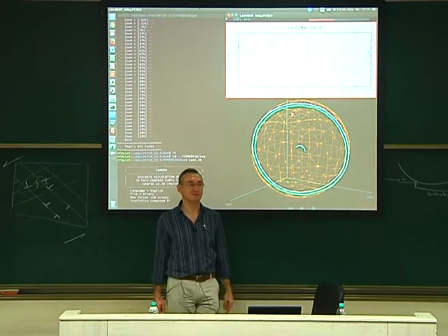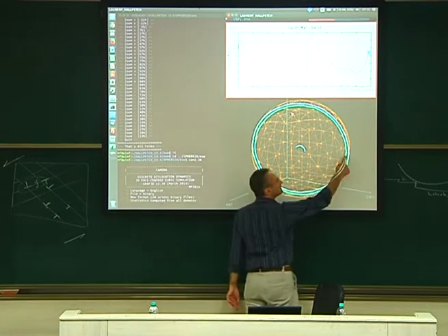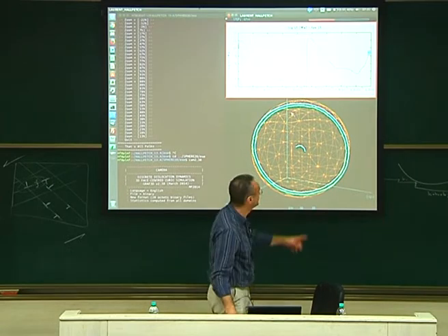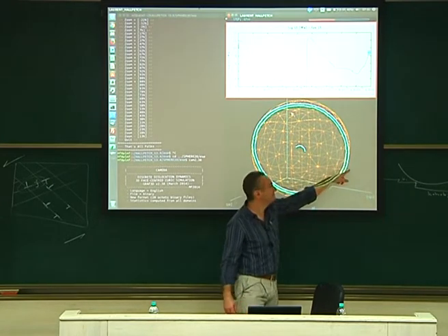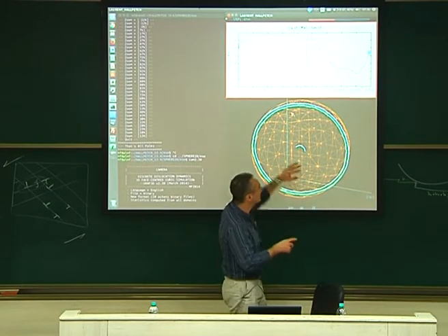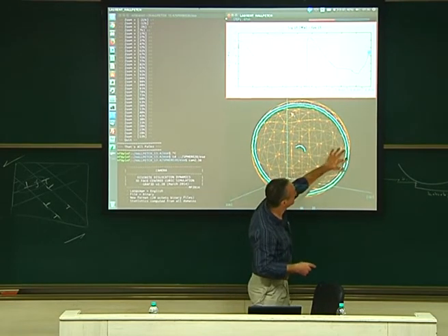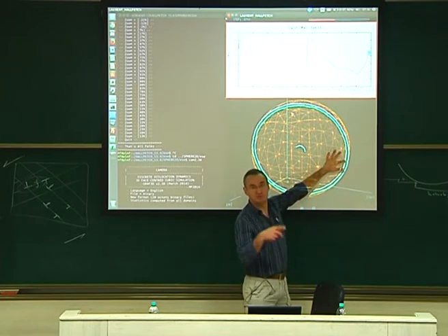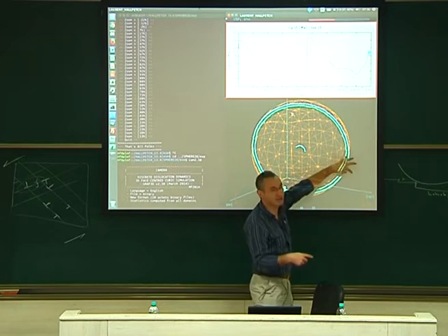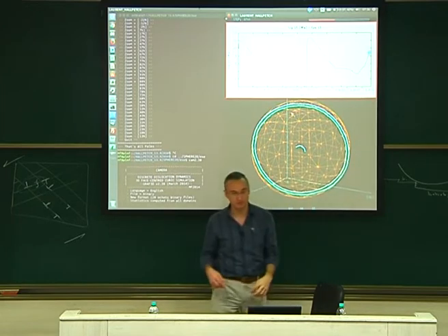See, this was your exercise yesterday. What is the distance of the second loop when you have a pile-up? So this is just because of the internal stresses from that guy on that guy, that they do not lie at the same place. Here you apply a shear stress tau, what you see here. This guy applies back a stress which is mu b over 2 pi (1 minus nu) times the distance a, and this equilibrates, and this gives you this position.